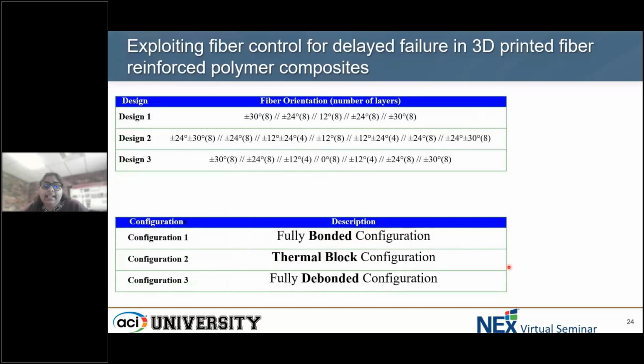What we went ahead and did is we established three configurations, which is we considered fully bonded configuration, which is the process of 3D printing just taking over and just continuously printing. Though it is not a perfect bond, we are considering that as a fully bonded configuration. The second configuration we established was what is called a thermal block configuration. I will explain with pictures what that means. And the third configuration we established is a fully debonded configuration, meaning the fiber orientations are separated without any kind of bond between them, and see what that leads to.